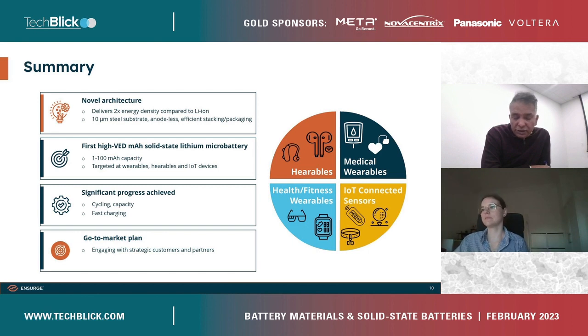Yes. So the overlay is essentially the packaging layers. The core cell by itself is a battery, but it is not a product. So that's of course the heart of the whole product, the unit cells. We stack the unit cells on top of each other to make the battery what we need. So the overlay is really a combination of packaging layers that we use, which we have to keep very thin. And when you have generation of lithium, you actually get a slight increase in the volume of the cell. And so it's important to have packaging which can accommodate a certain amount of that volume change. So it's meant to illustrate it. It's not to scale.